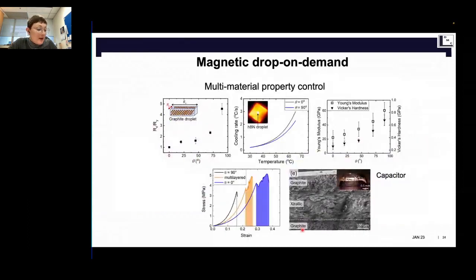Now, I was talking about devices and properties. So how is that actually interesting? That's where applying these to different materials is also interesting. So I'm going to take you through these graphs. The first one here, we use graphite platelets, same process, and then we tune the tilt of these graphite platelets in these printed droplets. And we measured the anisotropy between the direction Rx and the direction Ry. When all the graphite is horizontal, there is no anisotropy. But when you increase the angle, you increase the anisotropy in electrical conductivity, so that you can make functional devices that have high conductivity in one specific direction.